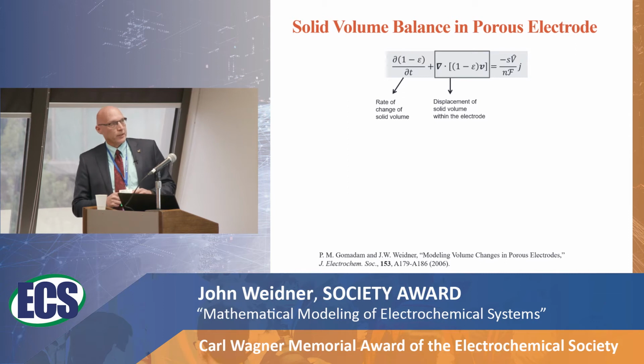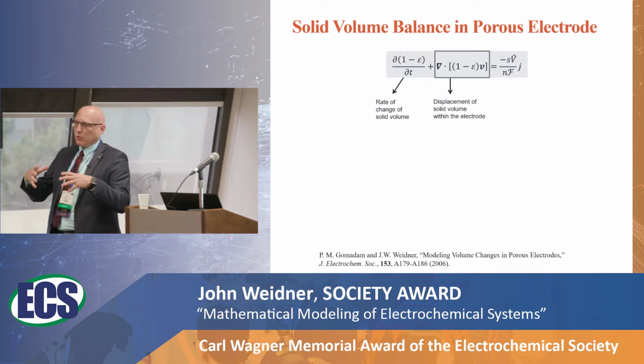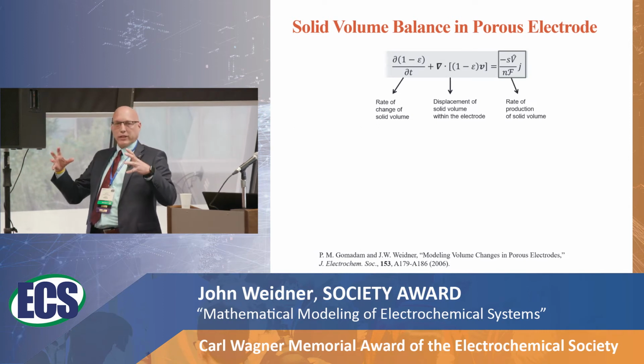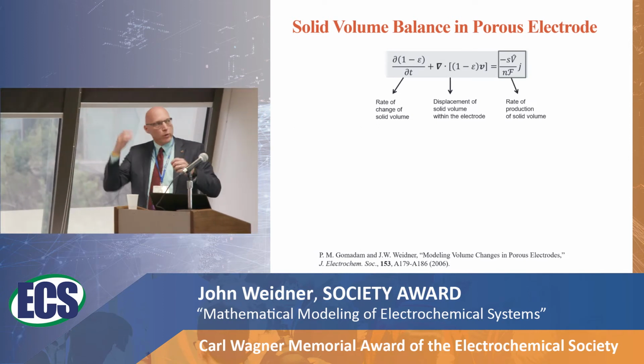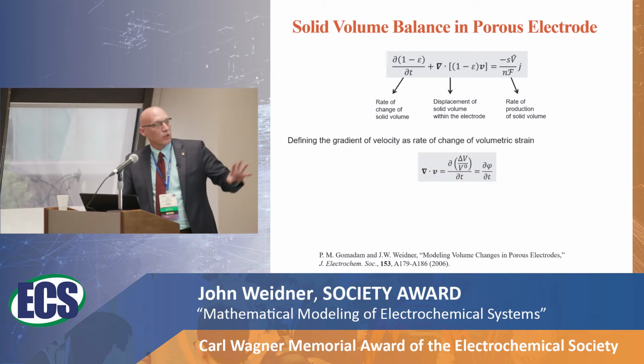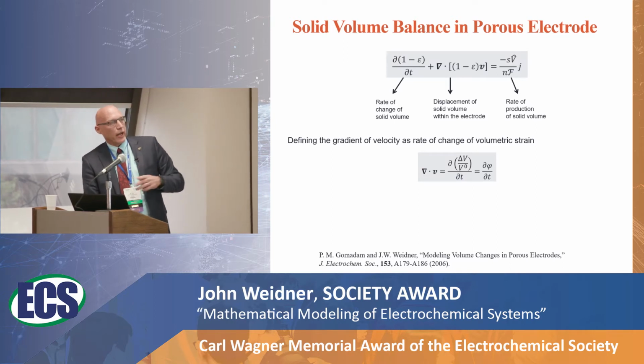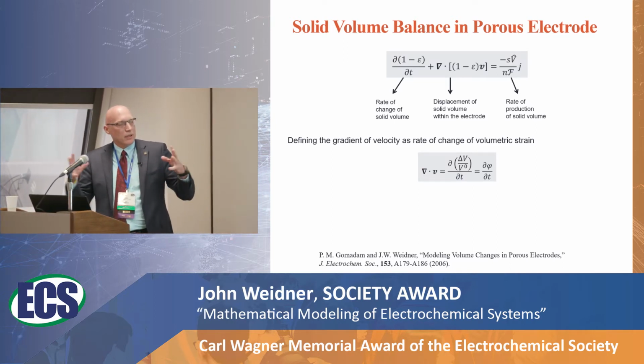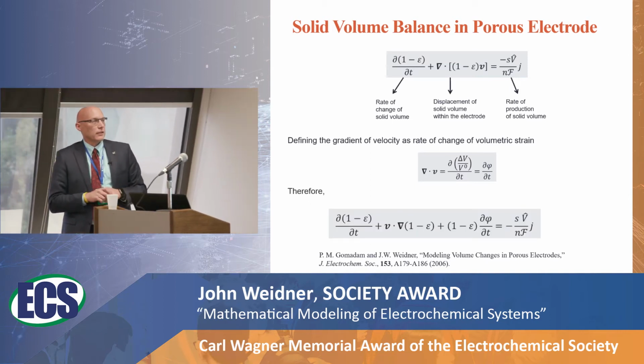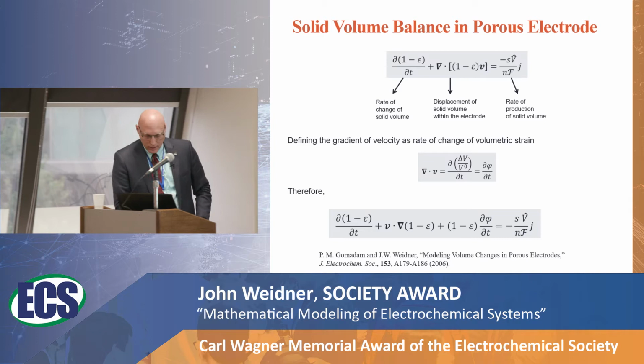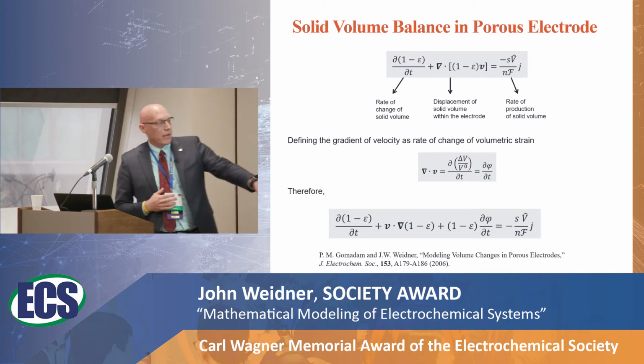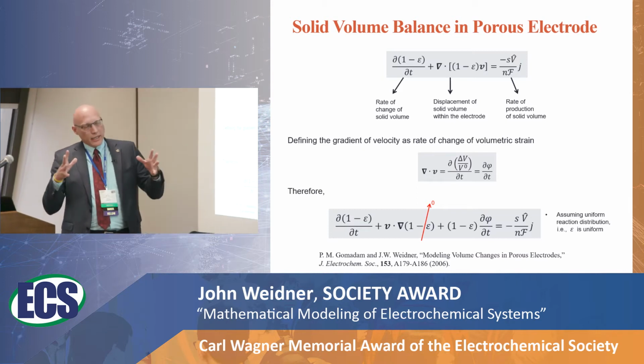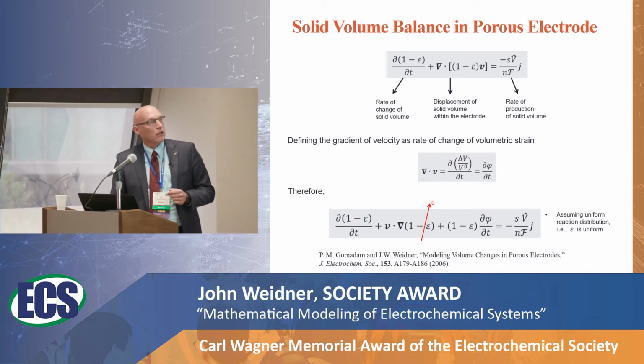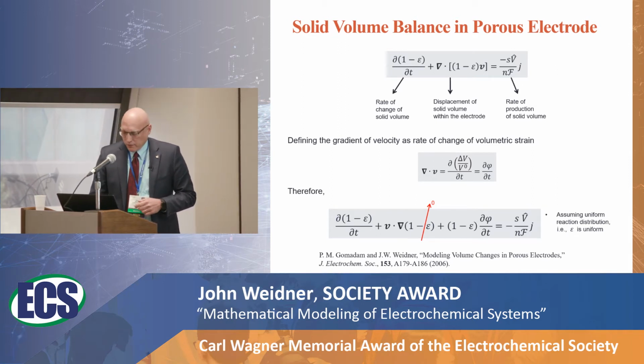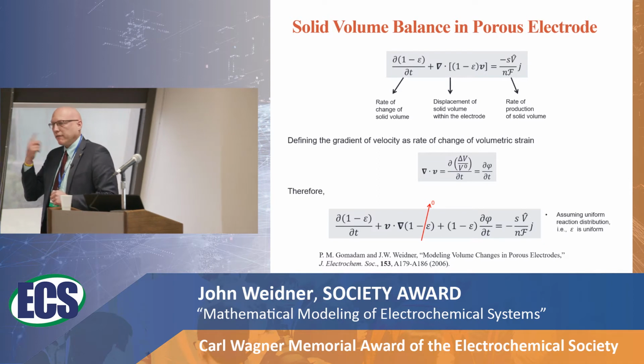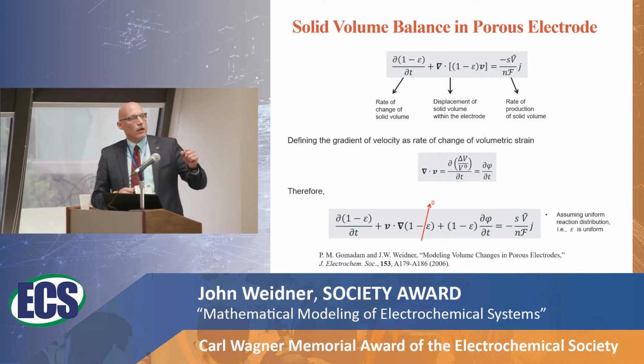solid balls expanding. And of course, a lot of people have looked at what is the stress and strain that's built up in a ball that's expanding, or active material that's expanding. We wanted to extend it to the porous electrode. So we were able to relate that velocity change to a volume increase, and it turns out that middle term is fairly small. So again, we basically have a porosity change, and an expansion of the electrode is related to the local reaction rate. And for the longest time, we couldn't, again, figure out exactly how to divide that out, because what we've